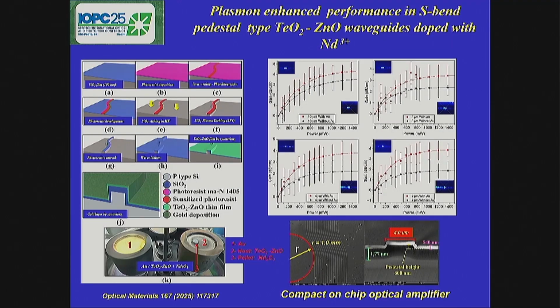Now, using the same steps in clean room, the same experimental setup, and the same pedestal architecture, we only changed the configuration, as you can do now with that microwriter, and we used the S-bend configuration and performed the same measurements to determine the relative gain in these 2 situations, with and without gold nanoparticles. As in the other case, we observe an enhancement of more than 8%,